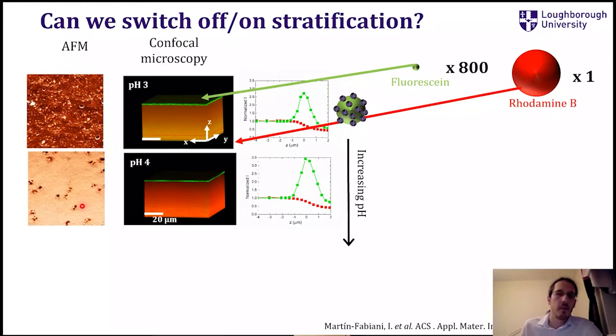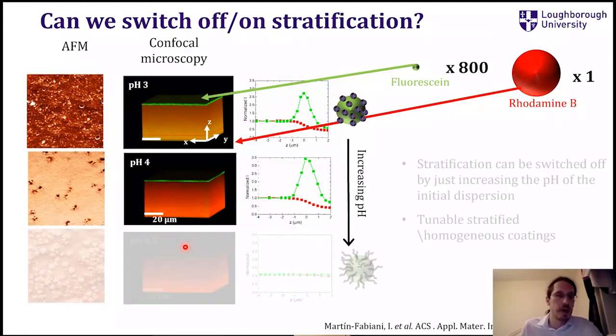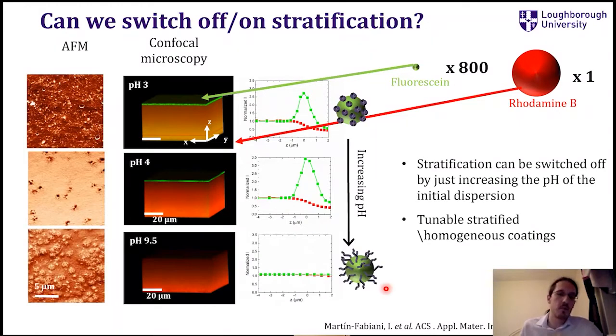surface. But when we go to pH 9.5, then we see that the green layer is not present anymore, and the AFM is saying that we have loads of large particles at the top. So we have increased the size of the small particles, and that has resulted in this stratification disappearing. So why did this happen?